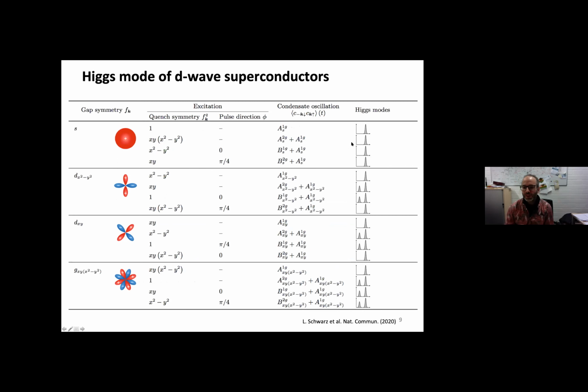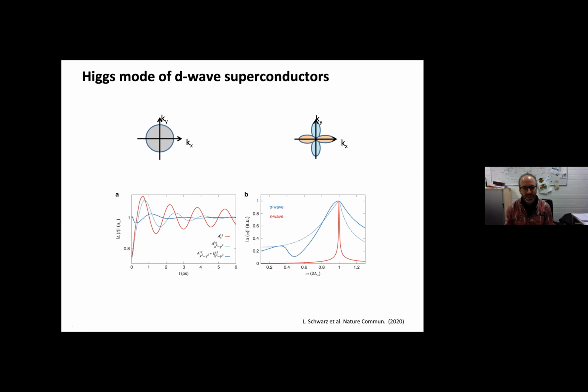And from this, you would get then a certain Higgs spectrum for your oscillations. And then depending on this Higgs spectrum, you could then map back to the oscillating order parameter of your superconductor in the system. And the goal here is now to show this for this important class of the D-wave superconductors, which is this dx square minus y square symmetry. Of course, in this case, we already know the oscillations, but now we have to show, can we really drive these Higgs modes in this system?